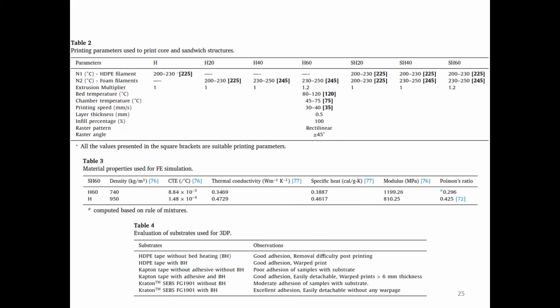because the first layer which we deposit has to adhere to the base until the printing is done, until the sample gets cooled completely within the chamber or within the build volume, whatever additive manufacturing method you are using. What does this mean? I'll show you in the subsequent slides, wherein we observed that until the final layer got deposited, everything went perfectly fine. But when the sample starts cooling, the warpage creeps in, especially for such multi-material, multi-functional materials, wherein the sample completely gets lifted off and bends permanently. So it is not that we need to just bother about adhesion of the first layer to the bed until all the layers are printed. It is until the cooling of the sample to room temperature. So that is very crucial.